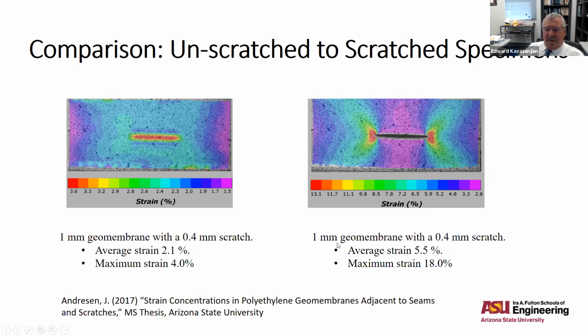And then here's a geomembrane with a deeper scratch, a 1 millimeter geomembrane with a, whoops, something's wrong here. Oh no, these are both 0.4 millimeter scratches. So I take that back. These are both scratches to 40% of the membrane thickness. Keep in mind that these scratches don't go all the way across the membrane. They were just over a limited section of the membrane, which we think inhibited the strain a little bit. But again, here we have an average strain of 5% and a maximum strain of 18% around the scratch. So these strain concentrations around scratches are valid. They really do exist.